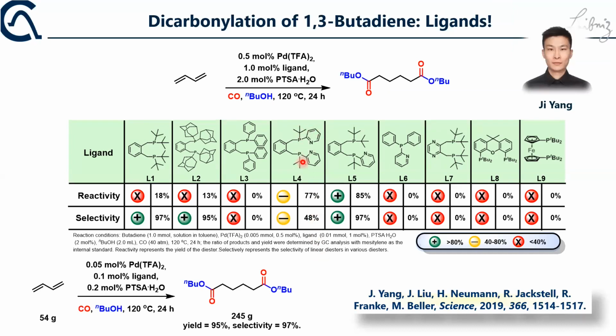And if you see, this ligand has 2 pyridyl groups, this has none. We thought the sterics is very important. The increased sterics of this system is very important to get the selectivity, and the presence of the pyridyl unit is very important for the activity. So what if we build a ligand which is in between these two things, still has the increased sterics, but also has this pyridyl group? And this is the Hemaraphos built by G for the first time. And as you can see, it combines the best of 2 worlds.